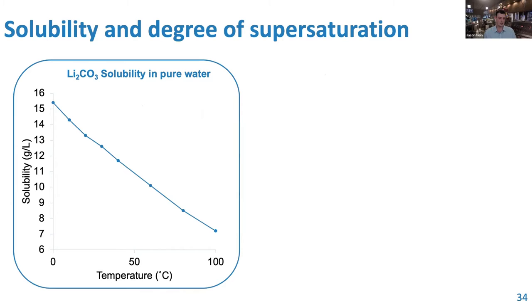You know, having materials that behave this way is one part, but the biggest thing is it's actually a relatively shallow solubility curve. The difference in solubility between very cold and very hot is not enough to do this as a simple batch crystallization and hope to get good mass recoveries from a fully soluble to a fully insoluble material.